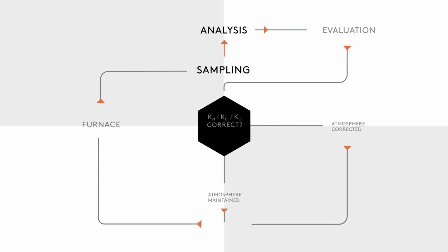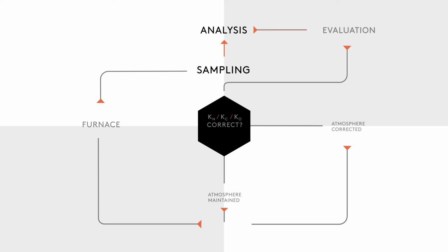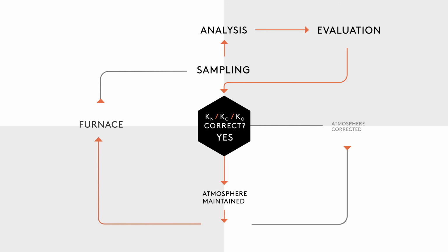Once automated, the control loop adjusts the flow of ammonia to the thermochemical reaction taking place in the furnace, depending on the total surface of the components, the surface of the furnace as well as the fixturing. It allows us to increase or decrease the usage of ammonia. If necessary, it dilutes the atmosphere even more to adjust to the conditions inside the furnace.